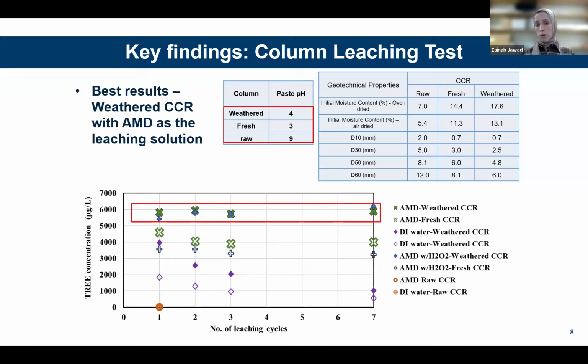And that was evident through the results of the paste pH. We know that a value of less than 6.5 means that the material under testing has already gone through the weathering process and has already generated acidic sulfate salts. And we can see that the weathered and the fresh refuse were less than 6.5. Well, when we compare that to the raw, we can see that it has a high number, and the results were insignificant for the raw refuse, almost 0 for total REs, and that is indicated by the orange circles in the figure.